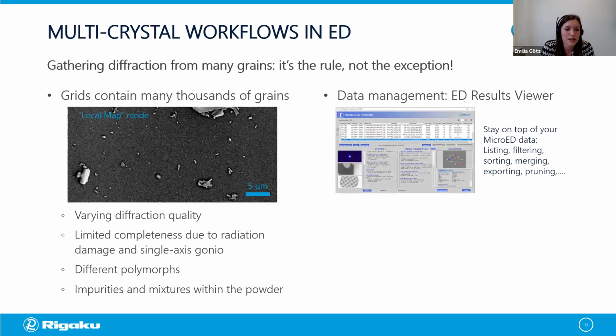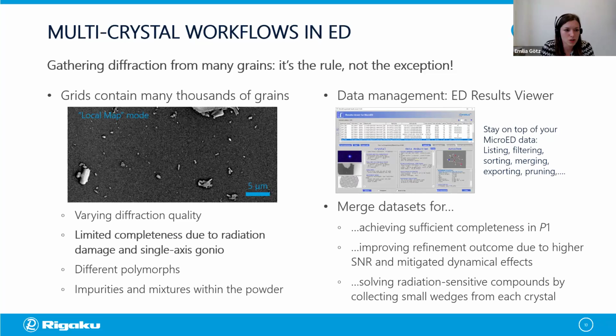In XtaLAB Pro, we have a specific tool for managing many crystal data sets, which is called the ED Results Viewer, which allows you to stay on top of collected data for many crystals and allows to list them, filter them, sort them, and one of the most important ones, merge them. So you typically need to merge data sets to achieve sufficient completeness for structure solution, especially for triclinic structures. But even for higher symmetries, merging data sets will often result in higher signal to noise ratio and a better quality of the data set. And it will also mitigate artifacts arising from dynamical diffraction if you still refine them in a kinematical approximation.